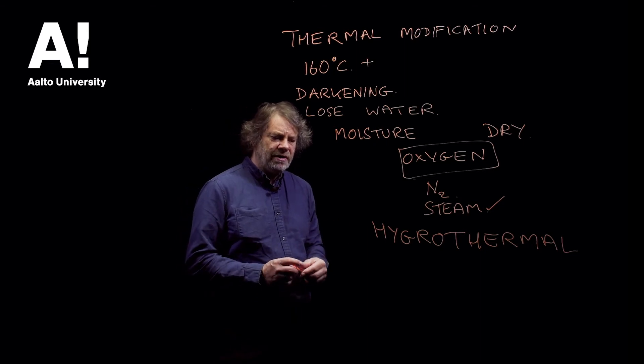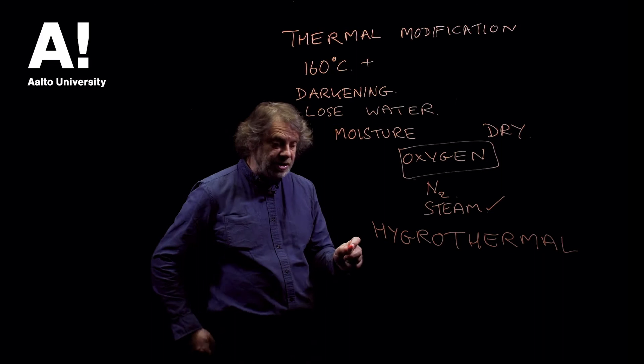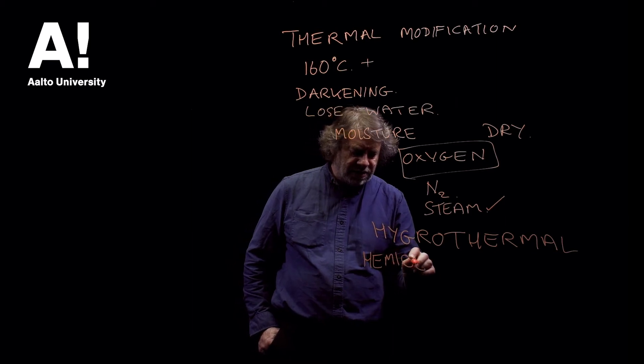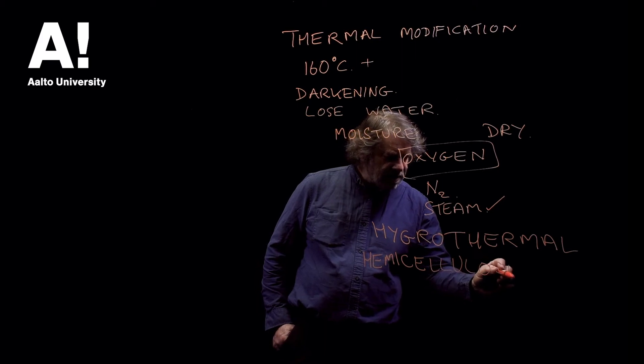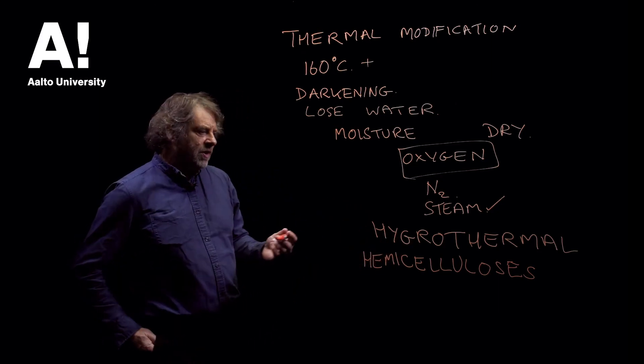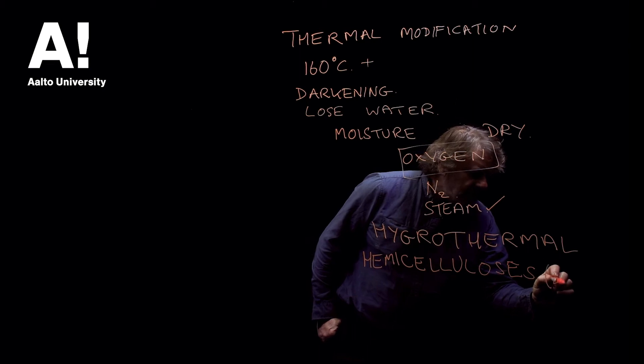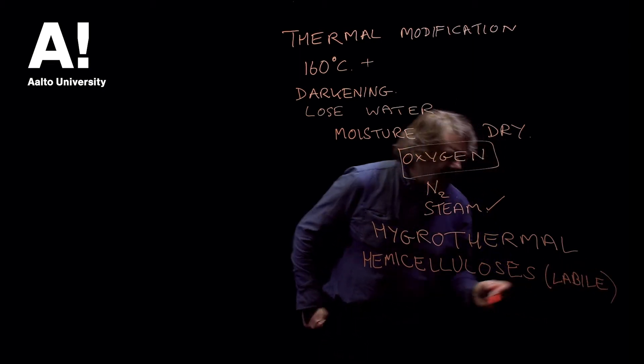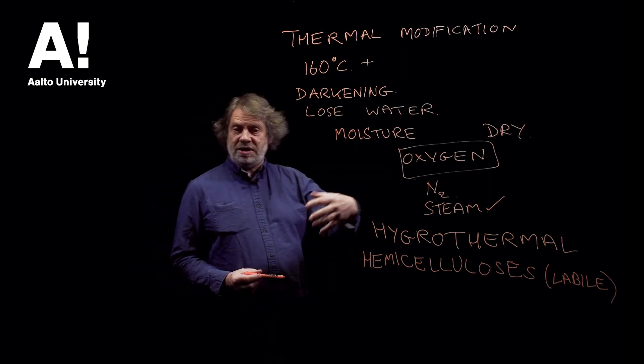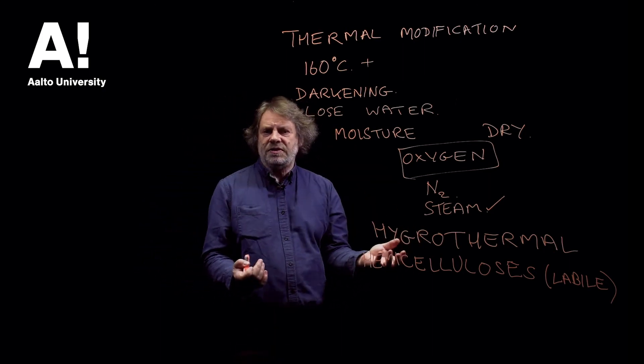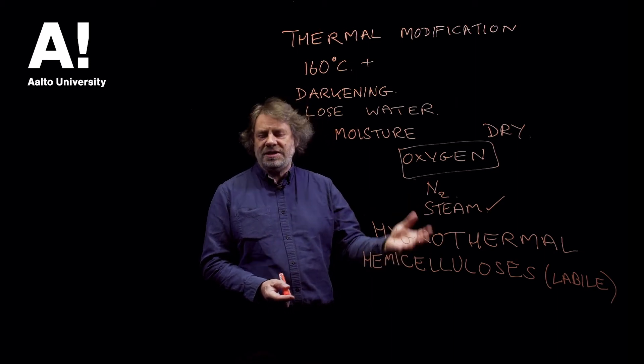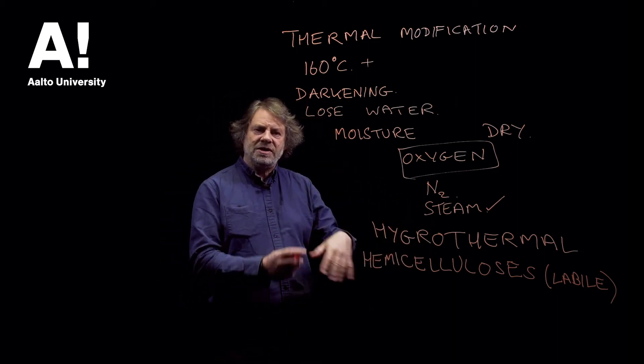The types of degradation reactions that are encouraged, which take place in thermal modification, involve the hemicelluloses degrading. Those are the most susceptible part of the wood polymers — the hemicelluloses — so they are the least thermally stable, or thermally labile, which means less stable and more susceptible to degradation, particularly when you get the presence of moisture. The hemicelluloses have got acetyl groups on them; those acetyl groups are quite easily driven off, particularly when there's moisture present. That generates acetic acid, which starts attacking the hemicelluloses, causing hydrolysis.